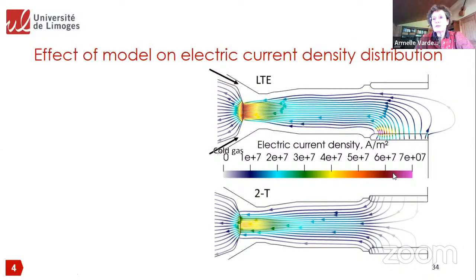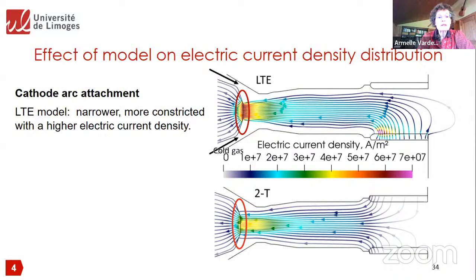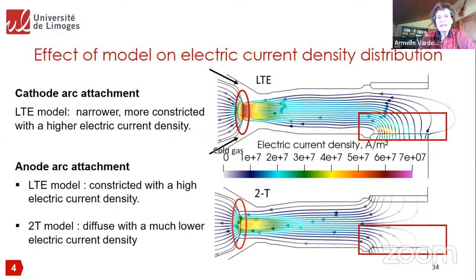If we look at the results we get with the LTE and two-temperature models for the current density distribution, you can see on this picture some striking differences at the location where the arc attaches. If you look at the cathode attachment, it's much more constricted and narrower with the LTE model. Now, if we look at the anode arc attachment, this is a striking difference. With the LTE model, it's constricted, while with the two-temperature model, it's diffused.